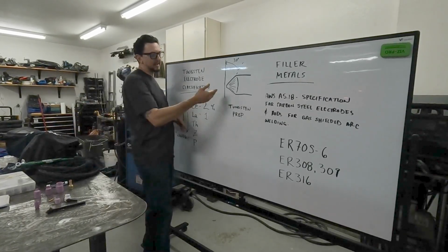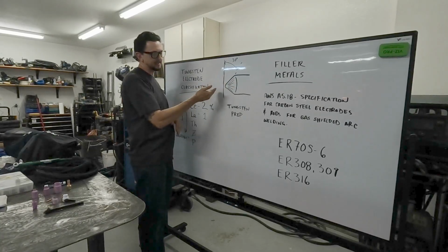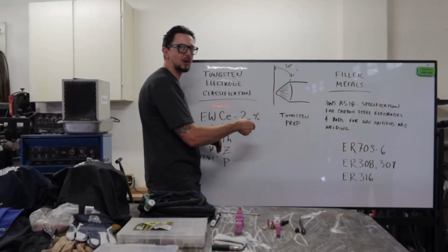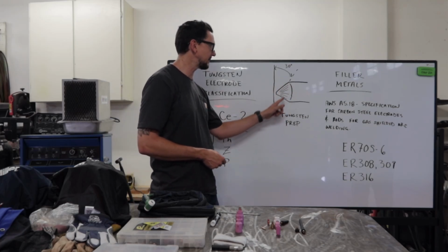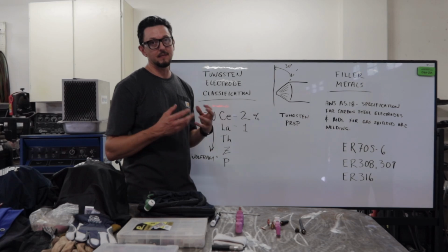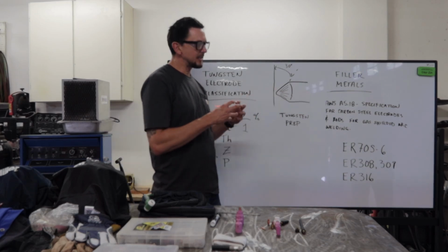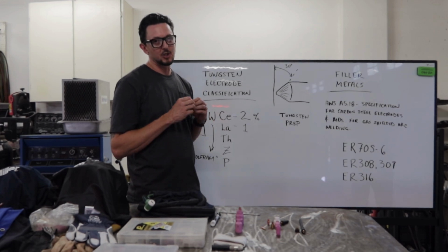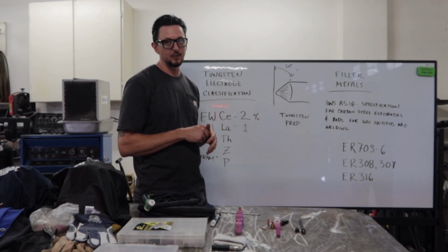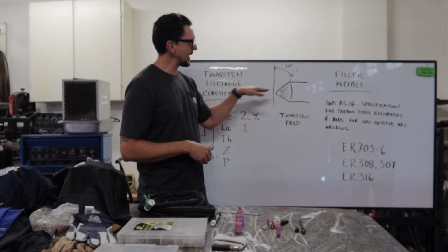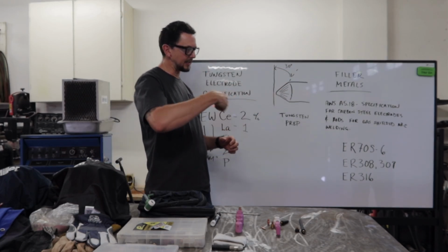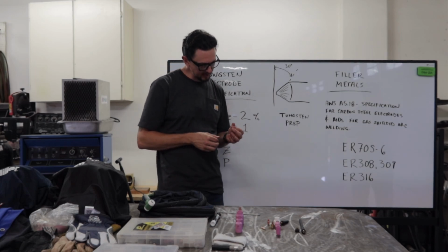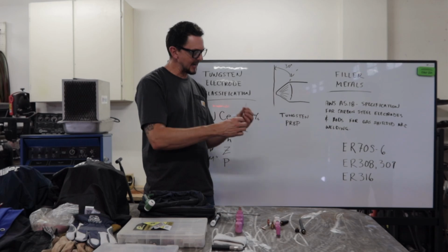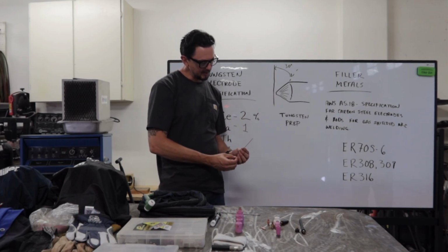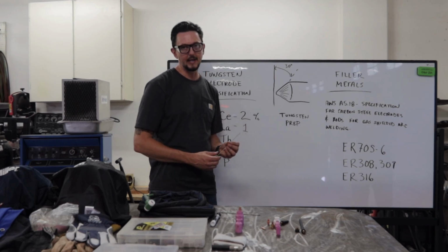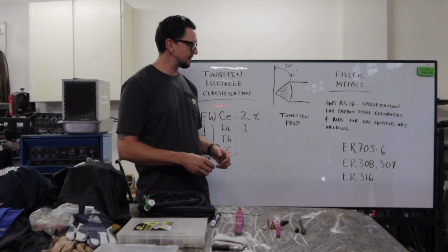Okay, one other important thing, we always want our grinding marks to go lengthwise. So we don't want radial grinding marks on there because that creates ridges going around that will just give the tungsten opportunity, as it expands and contracts with the heat, to just pop off and end up with a tungsten inclusion in there. So we want the grinding marks to go lengthwise. So if you're using a radial wheel and you're grinding your tungsten on that, you wouldn't want to go to the side. You'd want to hold it straight up and down and turn your tungsten so that the grinding marks go lengthwise. Okay, so that's tungsten prep.